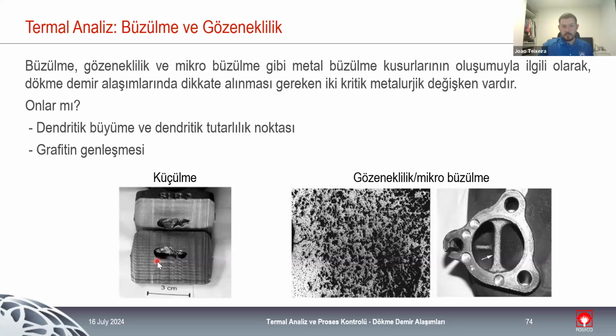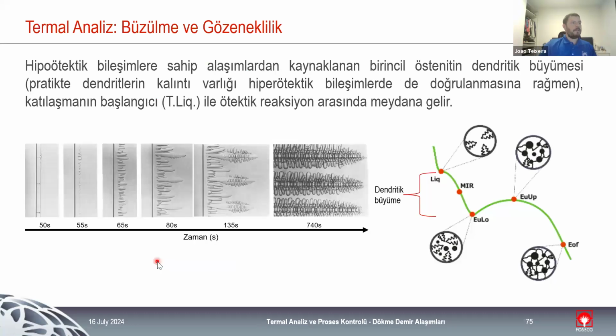And for this, the easiest way is to use solidification modules and programs like Magma to understand where the critical points of the solidification are, for us to counteract with the correct position of sleeves. And so the thermal analysis is important to control this dendritic growth, because most of the dendritic growth happens between the liquidus temperature and the eutectic low temperature. So this is another thing that we can take from thermal analysis when we are going to study thermal analysis, and when they are going to compare a lot of different production data with thermal analysis.